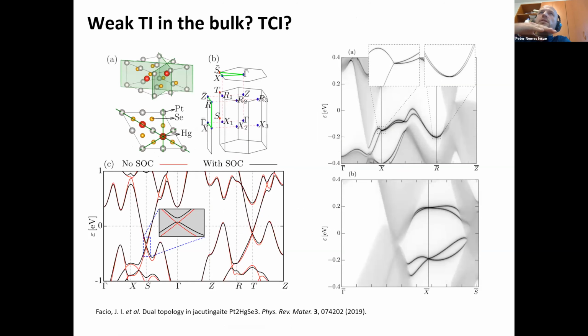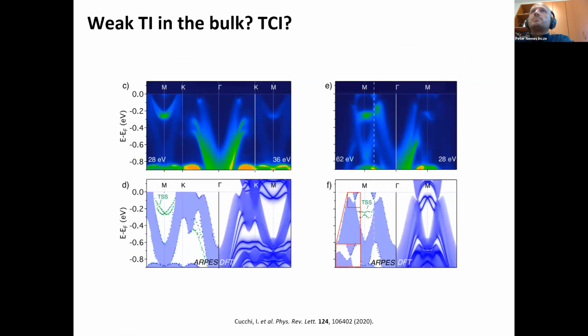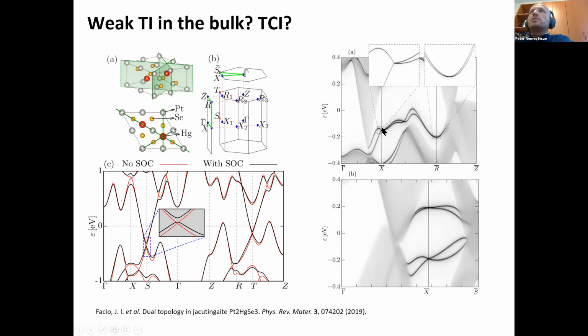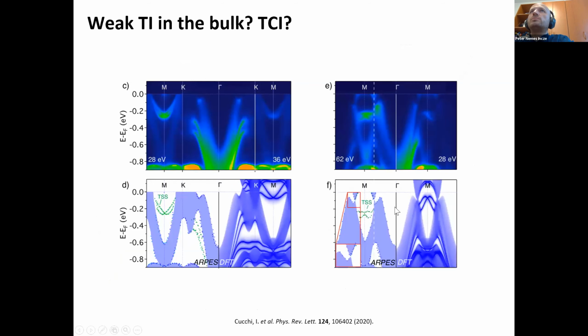in the bulk, so basically a stack of 2D topological insulators, it should also be a topological crystalline insulator, meaning that it has a non-zero mirror Chern number, and this leads to certain Dirac cones within the bulk band structure. Now, these Dirac cones are located and overlapped with bulk states. This makes it a little bit difficult to investigate in STM. Not impossible, but difficult. And these mirror protected Dirac cones have been shown to exist using ARPES measurements.